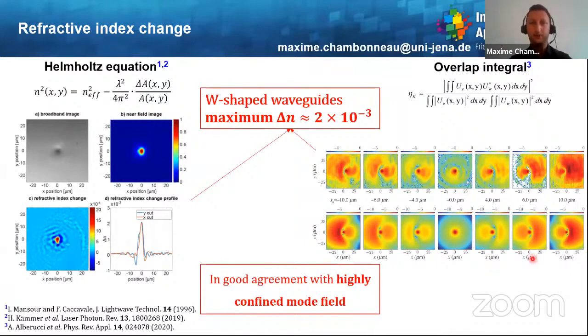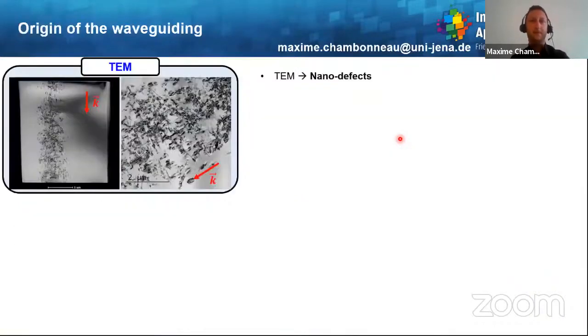So both methods we have employed allow us to conclude that the waveguides are W-shaped with a maximum refractive index around 2 × 10⁻³, which is in very good agreement with highly confined mode fields. Then one question is, what would be the origin of the waveguiding?